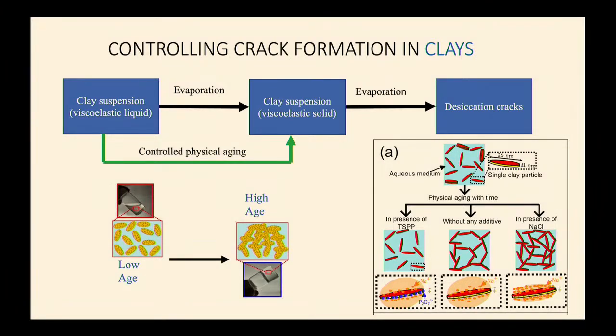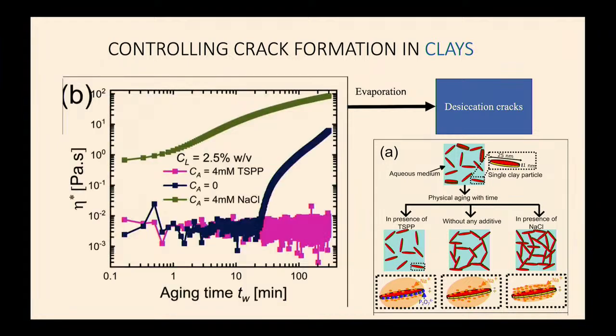So then the particles can now attract, because of the negatively charged faces and the positively charged rims, you form gels that are denser than you would have formed had there been no common salt at all. So these are the three kinds of samples we've made. You can think of them as going from repulsive particles all the way to highly attractive particles as you add salt.